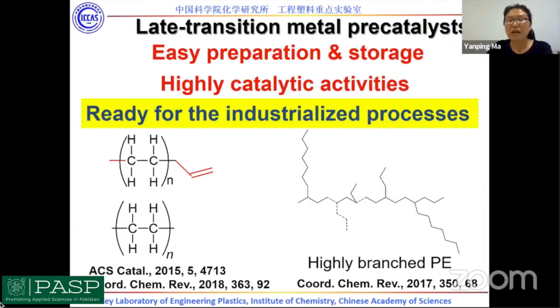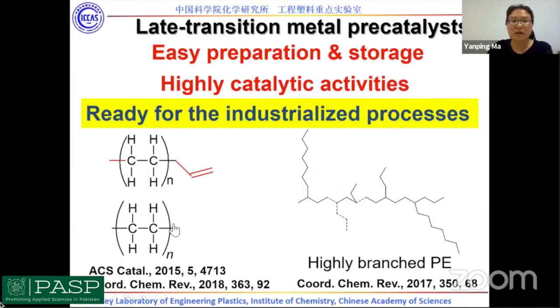So in summary, in our research work, we focus on late transition metal catalysts, and these catalysts can be easily prepared and stored, and they have highly catalytic activities. By these catalysts, especially the iron and cobalt catalysts, we can get highly linear polyethylenes, also highly linear polyethylene with vinyl end groups. By the nickel catalysts, we can get highly branched polyethylenes. It's exciting that by our iron catalysts, we have proceeded to the industrial process for alpha olefins.